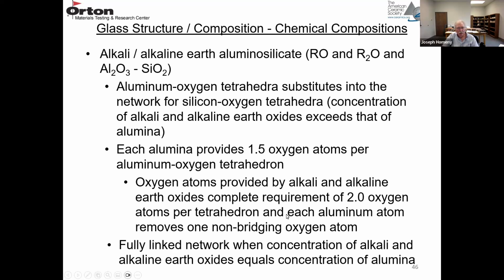So the other case, each aluminum atom provides 1.5 oxygen atoms per aluminum oxygen tetrahedron. So the oxygen atoms provided by the alkali and the alkaline earth complete the required 2.0 oxygen atoms per tetrahedron, and then each aluminum atom removes one non-bridging atom. So actually, this is the first case where you have excess alkali and alkaline earth oxides.